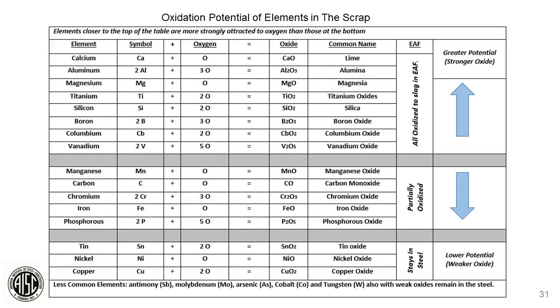So when you look at the elements that are in the scrap that we're melting, we get the top third there. These are elements that readily oxidize. They disappear very quickly from the liquid steel and go into the slag layer, and they're gone. The next ones towards the bottom, manganese, carbon, take a little bit more energy, a little bit more oxygen, and then they also go to the slag layers. Now, the bottom three never go to the slag layer at the steelmaking temperatures that we work at. So once tin, nickel, and copper get into the liquid steel in the furnace, we cannot get them out. So go to the next slide, please.